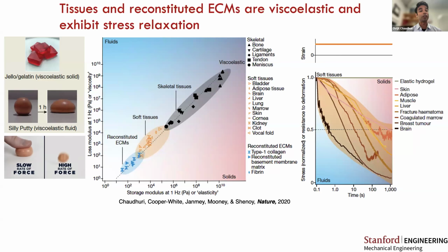So this becomes evident in stress relaxation tests. So in a stress relaxation test, we apply a constant deformation to a material, and we measure the stress over time. So in this measurement, the stress corresponds to the resistance to deformation. So what we see is that in an elastic hydrogel, the stress stays constant. So the resistance to deformation is time independent. Whereas for these various soft tissues, we see the stress is relaxed over time with a characteristic time scale ranging from seconds to thousands of seconds. And so again, this corresponds to the resistance to deformation relaxing over that time scale.